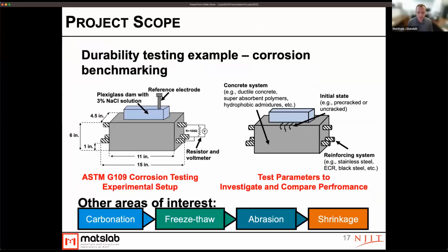Within this project, we did a range of different experimental testing. The primary of which that we'll talk about today involves corrosion testing. So we used corrosion tests to benchmark the performance of these fiber reinforced systems. And effectively what we did is we took small reinforced beams made of these different systems, and we exposed them to a 3% sodium chloride solution.